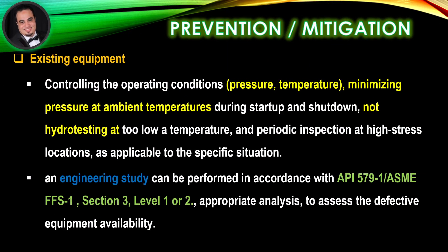For existing equipment, preventing and minimizing the possibility of brittle fracture relies upon controlling the operating conditions — pressure and temperature — minimizing pressure at ambient temperatures during start-up and shut-down, not hydro testing at too low a temperature, and periodic inspection at high stress locations, as applicable to the specific situation.